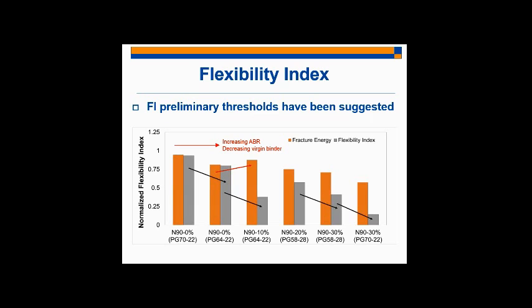However, if I use the flexibility index we've developed, I can see a much more logical, much more intuitive relationship between these mixtures. And what happens is, as I go from the N90 0% PG70 minus 22 to the 64 minus 22, as I'm softening the binder, I get a bump down in the flexibility index. The reason for this is because the 70 minus 22 is polymer modified. So it's just a better binder all around. It displays higher peak loads. It displays higher ductility. And so I get a bump down in the flexibility index. As I add 10% asphalt binder replacement, or 2.5% RAS, I get a further decrease in the flexibility index. Then I use a softer binder, a PG58 minus 28, and then I add 20% ABR, or 5% RAS, and I get a bump up, which was resulting from the softer binder.